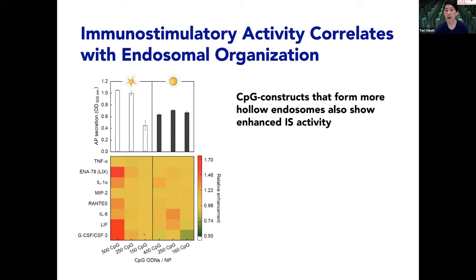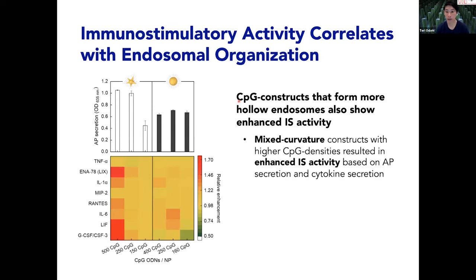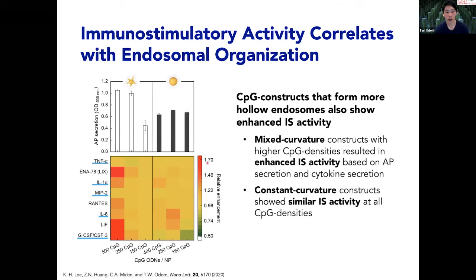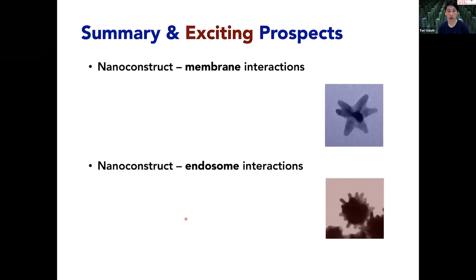And so what we can see is that these constructs here that form hollow endosomes, they also show enhanced immunostimulatory activity. And these mixed curvature ones we can validate both on the alkaline phosphatase secretion, as well as the cytokines that you see here. And then these constant curvature constructs, they just have the same or similar immunostimulatory activity at all densities. So what I like about this sort of fundamental system is that there's a spatial distribution of where the constructs end up, which results in a biological response.